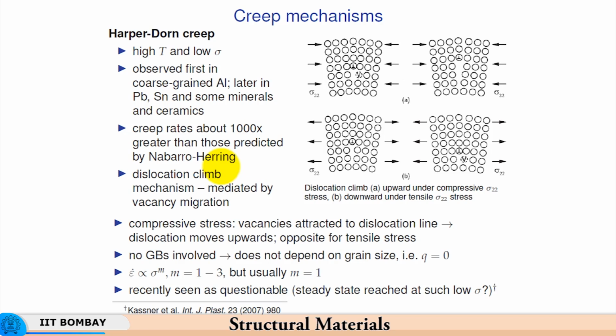So, when there is a compressive stress, vacancies are attracted to the dislocation line, and the dislocation moves upwards. The opposite effect is found for the tensile stress, meaning the vacancies get repelled from the dislocation line, and so the dislocation cannot move upwards, and therefore the creep resistance can increase. So, the creep rate can reduce. Basically what we are saying is that Harper-Dorn creep can explain the difference in the creep resistance under tension and compression. So, the creep rate under compression could be much greater than the creep rate under tension.